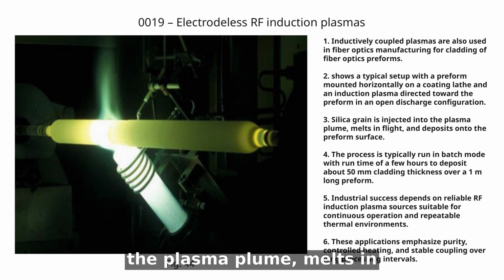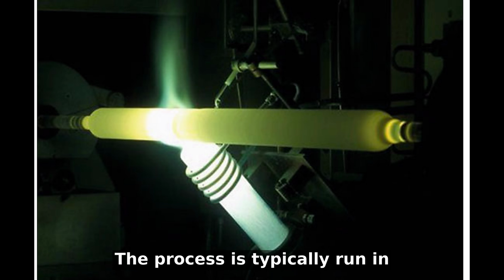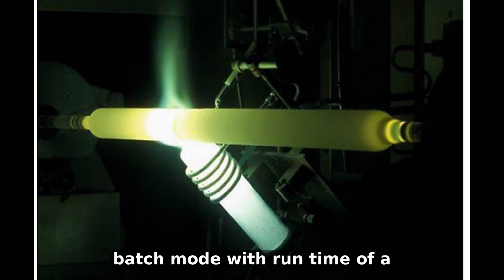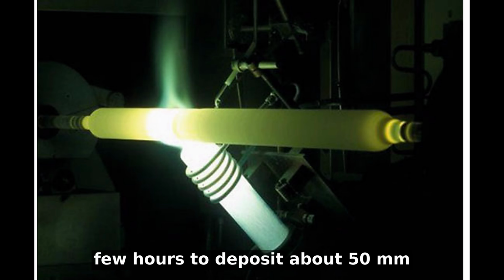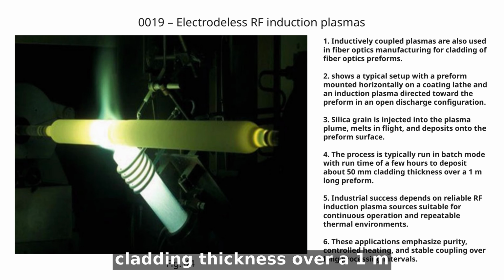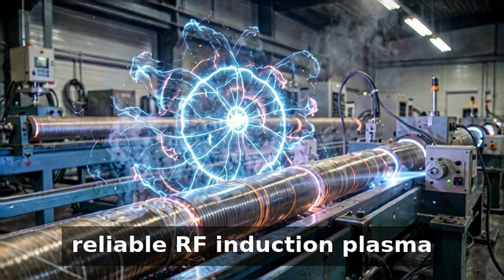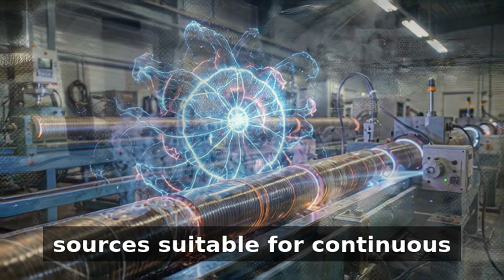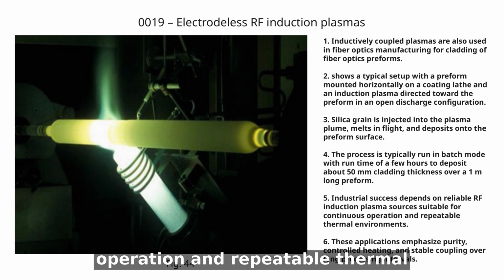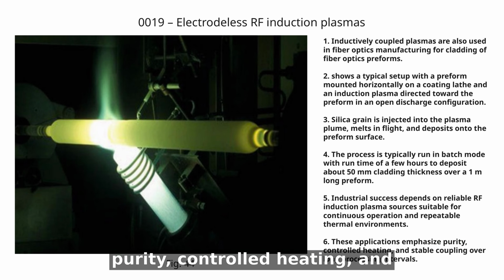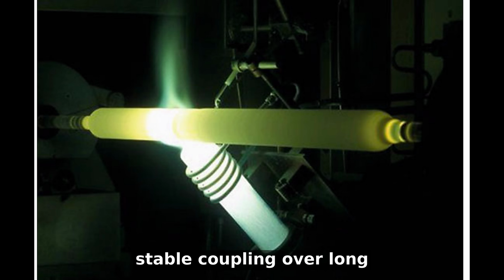Silica grain is injected into the plasma plume, melts in flight, and deposits onto the preform surface. The process is typically run in batch mode with runtime of a few hours to deposit about 50 mm cladding thickness over a 1 meter long preform. Industrial success depends on reliable induction plasma sources suitable for continuous operation and repeatable thermal environments. These applications emphasize purity, controlled heating, and stable coupling over long processing intervals.